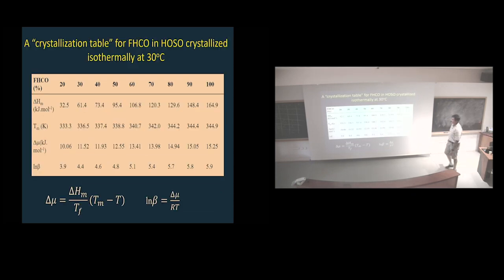And then you can come up with tables like this. For example, this is something that has a really high melting point, 20, 30, 40, 50, 60% of that in a liquid oil. And you measure your enthalpy, which goes up, obviously, because you have more solids, you have your temperature of melting, and then you can very easily calculate your chemical potential difference, and you can also put a number for the supersaturation. The problem, at least this is an advance relative to before, people would go, oh, look, milk fat looks different from fully hydrogenated canola oil. Wow. It's like, yeah, one has a melting point of like 60 degrees, and the other one has a melting point of 30. If you put it all in terms of what supersaturation they're experiencing, you probably find out that they behave very similar.